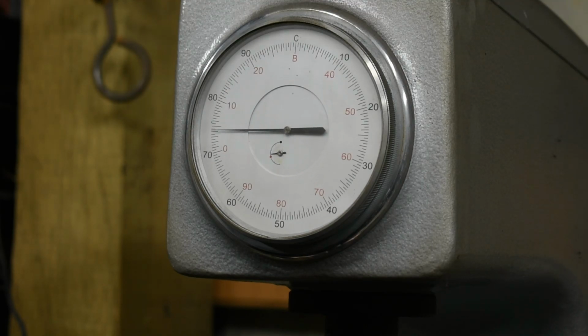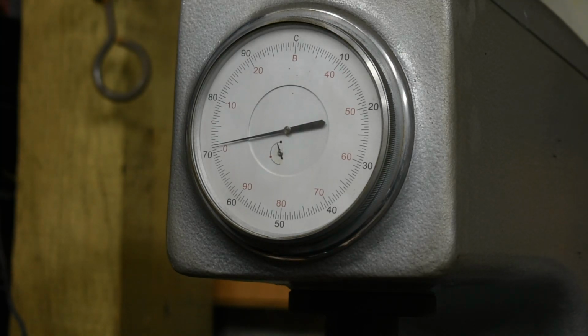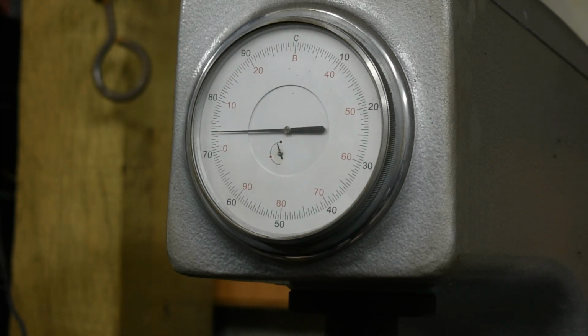Here's a close-up. We're coming around, applying the secondary load, watching the needle settle. And now we crank it back, lock it again. Now it's getting readings of 63, 63.5 at the highest. We're going to do another test.